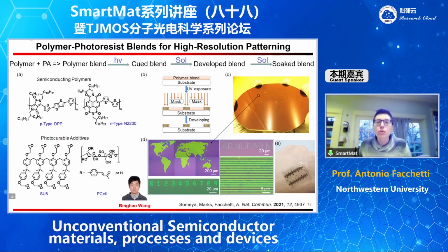There are several methodologies to do that, but we used a new method which involves taking a polymer, which can be P-type or N-type, and then blending it with a photocurable resist, which can be based on molecular epoxy, epoxide, or photocurable 2+2 cycloaddition chemistry. This is not so important. But the important thing is we can mix the polymer with the photocurable additive. We get a blend. The blend is spin coated on the substrate of interest, and then is UV cured. And then you need to develop to create your photopatterned semiconductor area. And then you can also soak this photopatterned area to a greater extent.